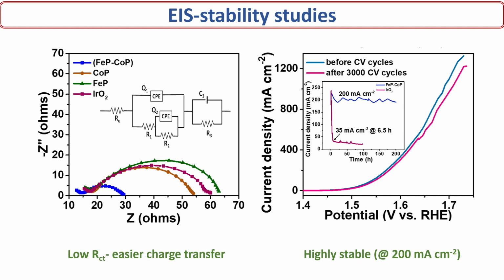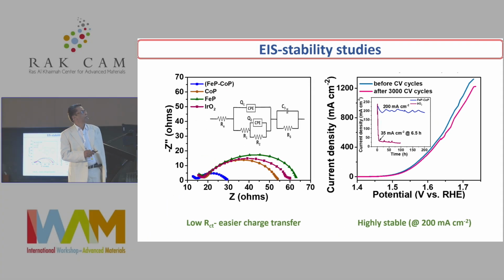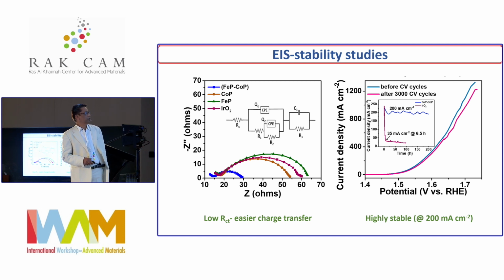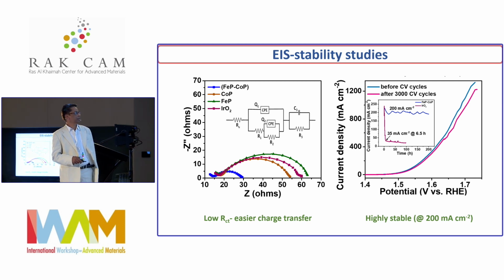Even the impedance analysis is very interesting. It shows very low charge transfer resistance, the low RCT value, particularly for the FeP-CoP compared to the other individual phosphides, indicating fast kinetics associated with the interaction at the heterostructure.